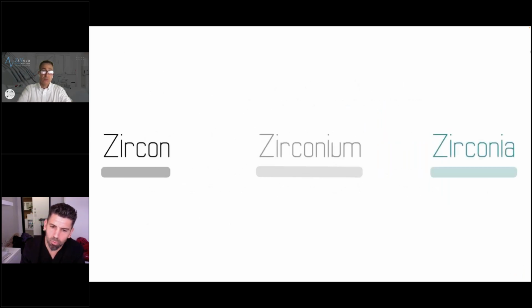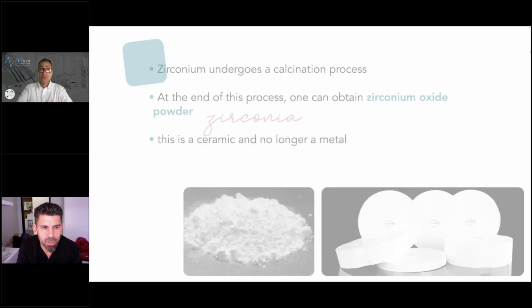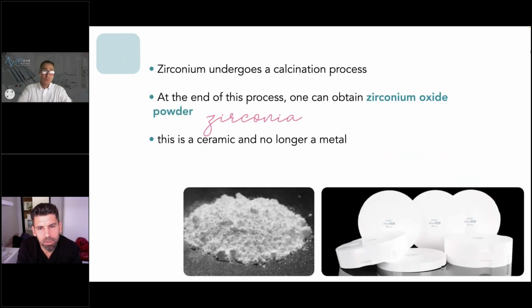Now we can take this material one step further, and zirconium metal can go through a calcination process, and at the end of this process, one can obtain zirconium oxide powder or zirconia, and this is now a ceramic and no longer a metal. So we need to be very clear that zirconium metal is very different from zirconia ceramic, and a lot of times the words are misused frequently.